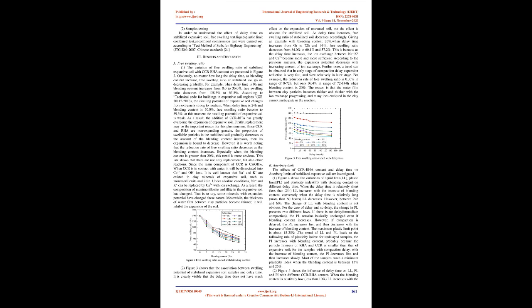Firstly, replacement may be the important reason for this phenomenon. Since CCR and RHA are non-expanding granules, the proportion of swellable particles in the stabilized soil gradually decreases as the blending content increases, then its expansion is bound to decrease. However, it is worth noting that the reduction rate of free swelling ratio decreases as the blending content increases. Especially when the blending content is greater than 20%, this trend is more obvious. This law shows that there is not only replacement, but also other reactions.